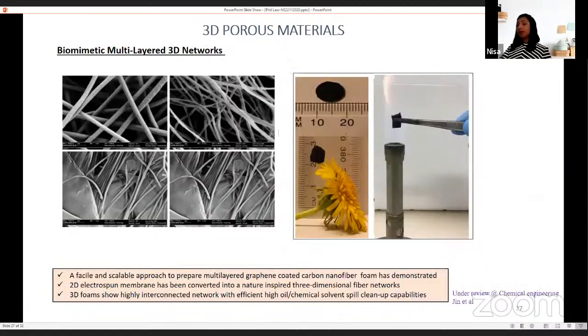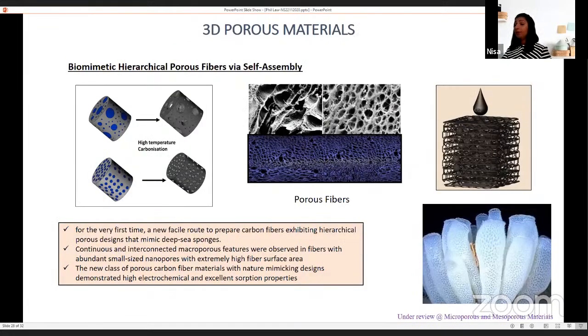So in our current research, we are combining the self-assembly approach with adding functionalities. By using this method, we are converting two-dimensional carbon materials into three-dimensional forms. In this particular work, we converted an electrospun mat into a three-dimensional form, and that's the way we found a highly interconnected network of nanofiber features that can bring efficient oil adsorption or chemical adsorption capabilities. We also wanted to look at what will happen when we scale up self-assembled nanostructures at macro scales.